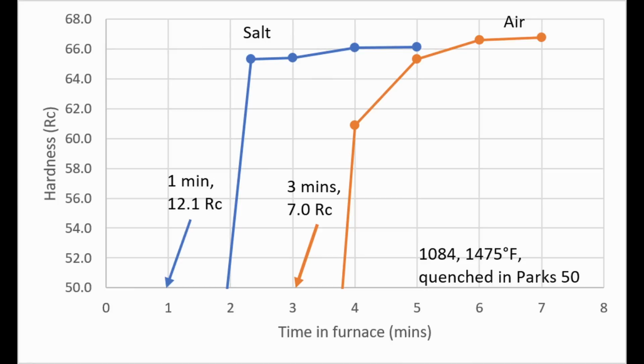Unfortunately, I was a little bit late with the 2-minute coupon. It was more like 2 minutes and 20 seconds. But by 2 minutes and 20 seconds, the 1084 was 65 Rockwell or so. So basically fully hardened, which means we had to have heated up close to the 1475 Fahrenheit that I had the salt bath set to.